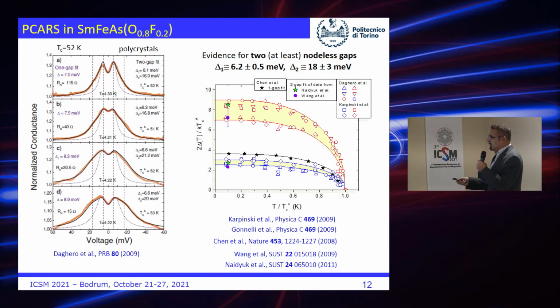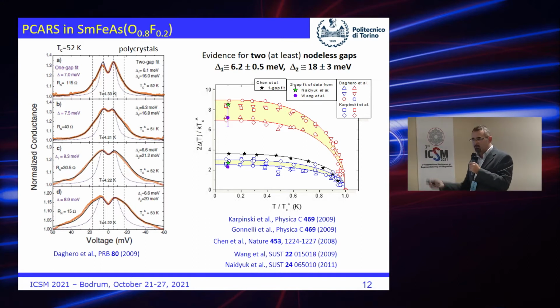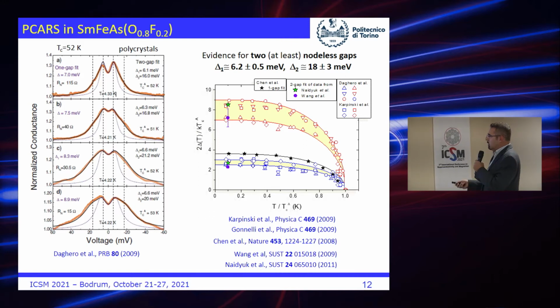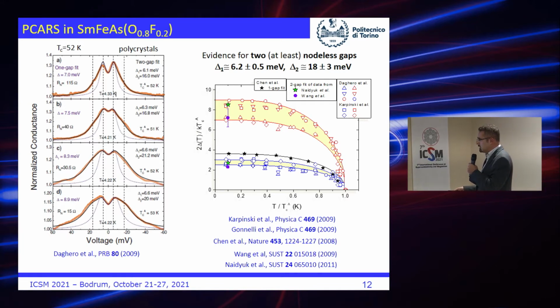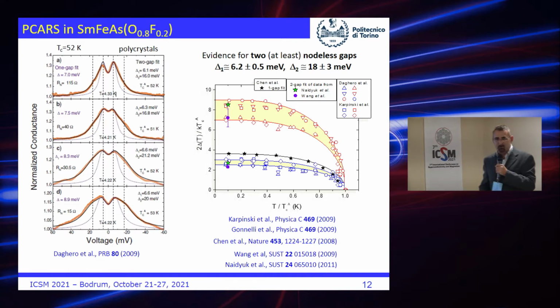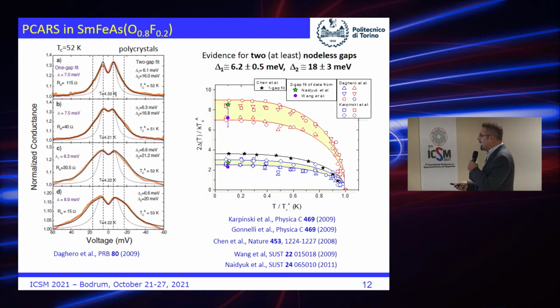If we put together the values of the gaps extracted from these curves, plus the values extracted from very many other curves, and you put together single crystals and polycrystals, you have this picture. Since we use different crystals and different samples, we have to normalize here and here. So this is actually 2 delta over k T_c as a function of T over T_c. These are also your data, Yuri. These are the fit of your beautiful, very early data on samarium. And there is a substantial agreement.